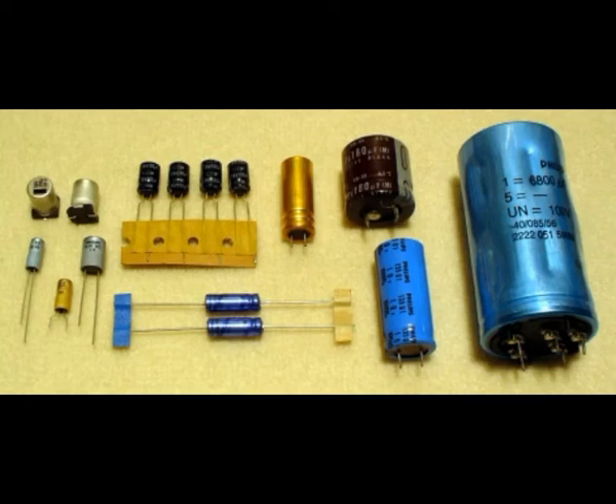Capacitors manufactured during and before World War II sometimes suffered from contamination during manual manufacturing, and in particular chlorine salts were often the reason for corrosive processes leading to high leakage currents. Chlorine acts on aluminum as a catalyst for the formation of unstable oxide without becoming chemically bound itself. After World War II, this problem was known, but the measuring equipment was not accurate enough to detect chlorine in very low ppm concentration.